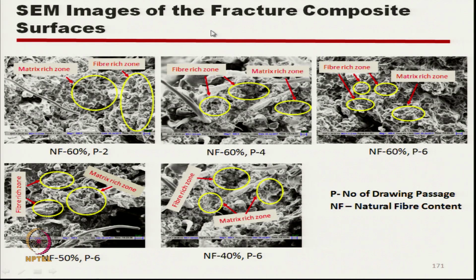This is the same image, showing a similar effect: fibre rich and matrix rich components are also there, but if we see, these are the fibre and matrix zones. Here, interestingly, at 2 passages the matrix rich and fiber rich zones are larger in size, but as we go on increasing the number of passages, these matrix zones and fiber rich zones become smaller and smaller. That is obvious because of the proper blending.